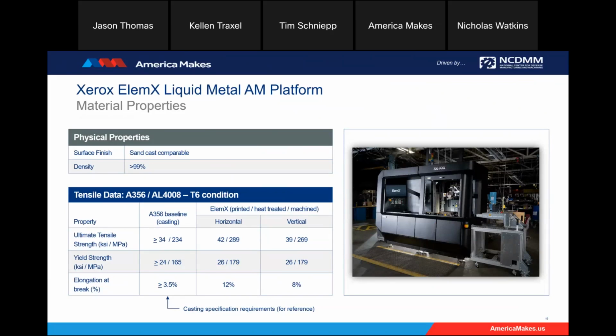So as you can see, the tensile strength, both yield and ultimate, not only meet the specification requirements, but are pretty isotropic in performance overall. Some anisotropy does start to show up in elongation at break, still well above the spec limits there. Ductile failures, which is always a positive.